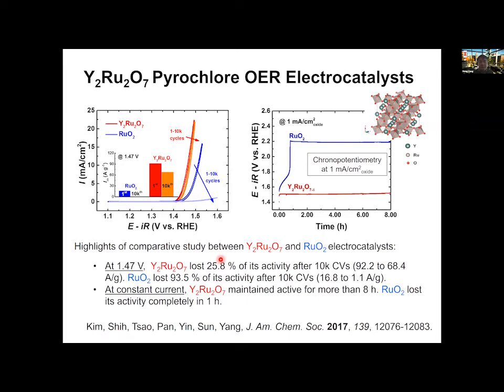And this was inspired by a paper published on lithium-based battery studies, and they recorded that the pyrochlore type of prototype structure could share some stability in acid. So that's one of the reasons we screened a range of pyrochlores, and the yttrium-based system appeared to be quite stable. If you look at the CV cycles under the proper conditions for the oxygen evolution system, you can see by doing 1,000, 10,000 cycles, very little degradation occurs.